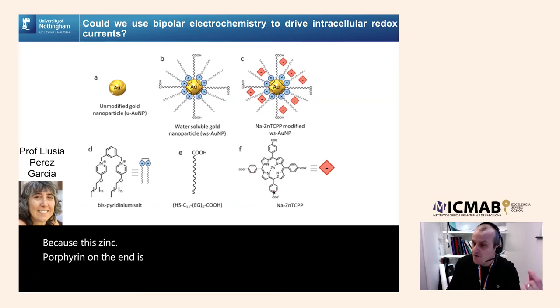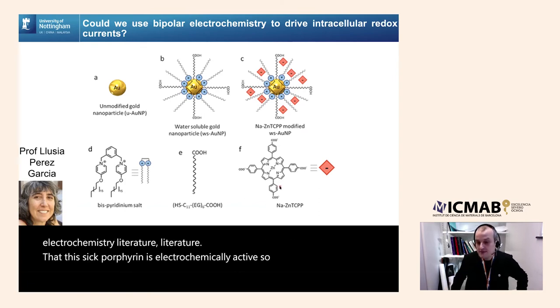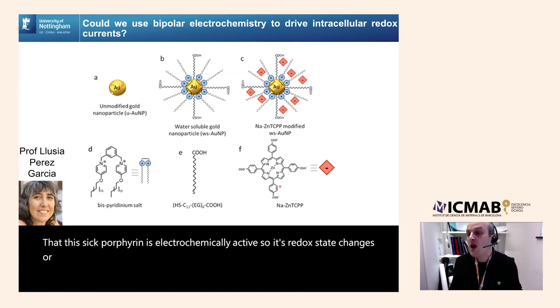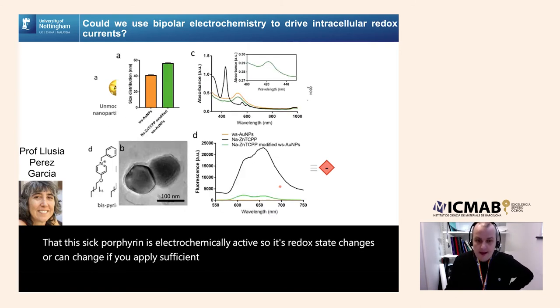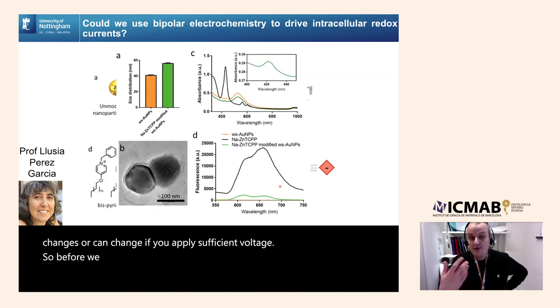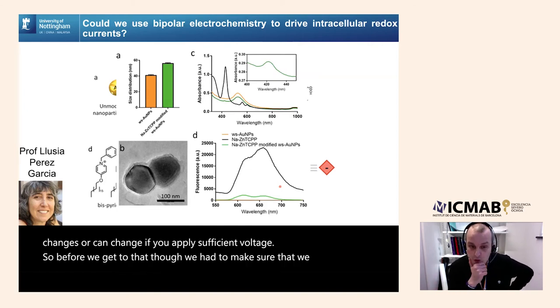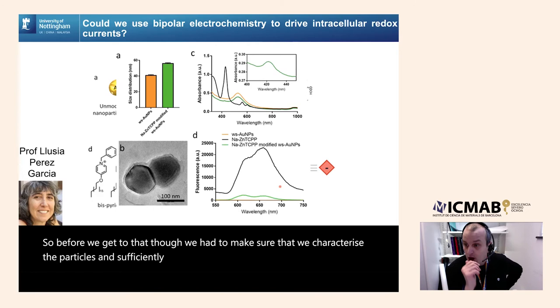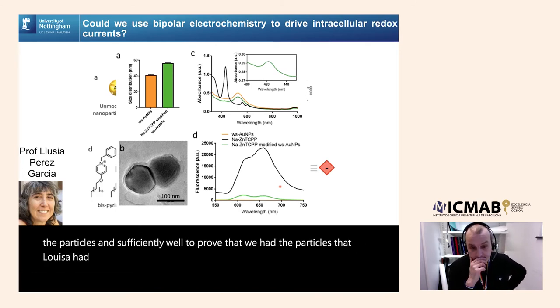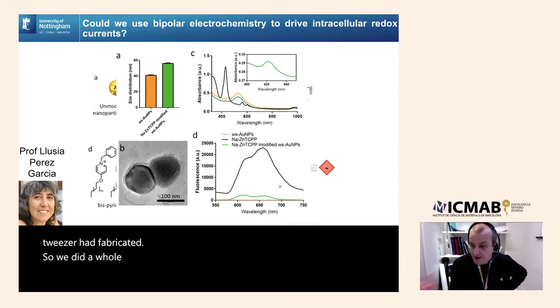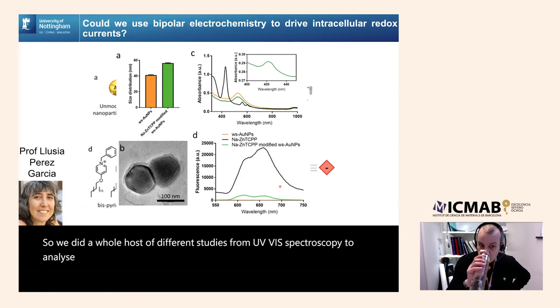And we also know from the electrochemistry literature that this zinc porphyrin is electrochemically active. So its redox state changes, or can change, if you apply sufficient voltage. Before we get to that, though, we had to make sure that we characterized the particles sufficiently well to prove that we had the particles that Luisa had fabricated. So we did a whole host of different studies, from UV-vis spectroscopy to analyzing the fluorescence, through to TEM and SEM.